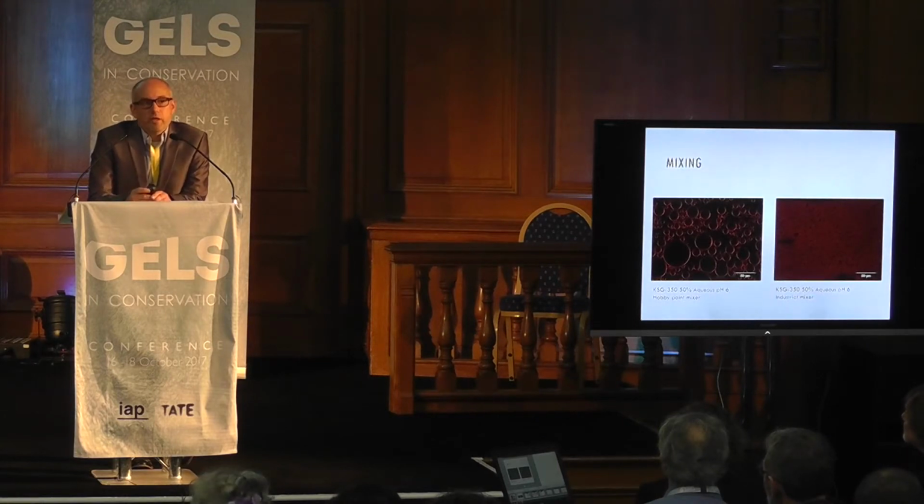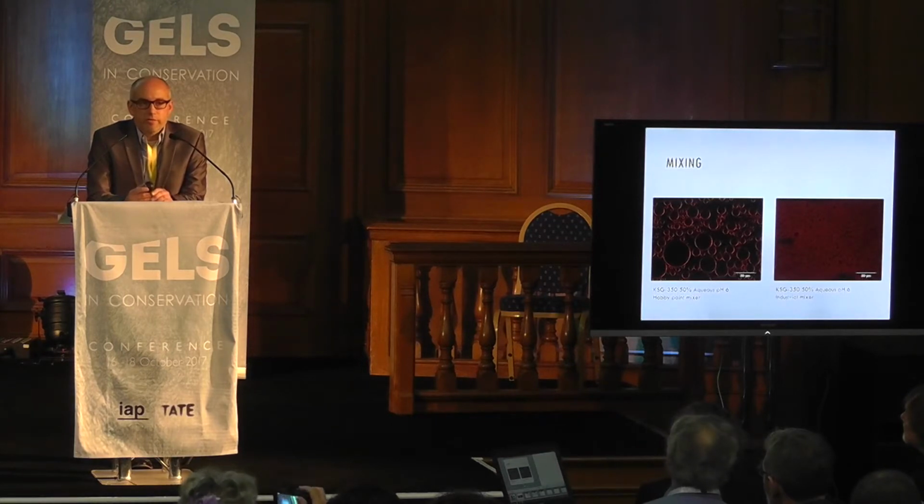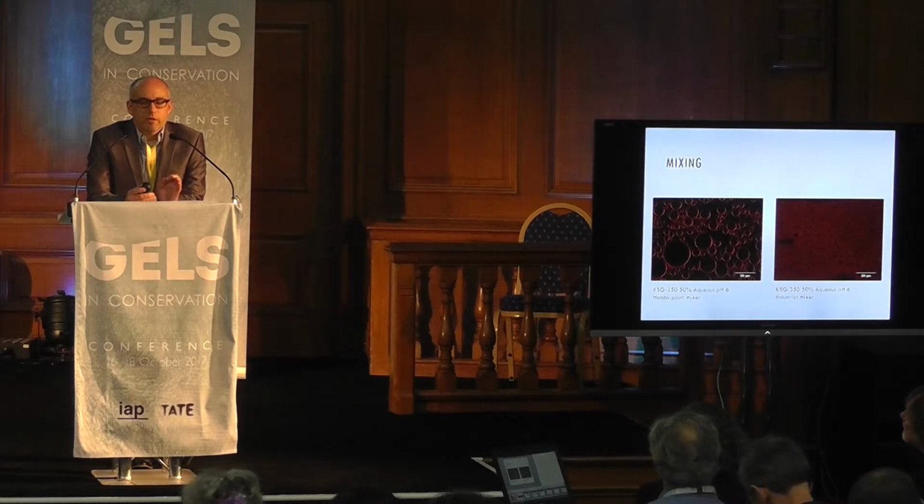One note on mixing. If you mix them by hand, shaking, sort of as Chris does, you're going to wind up with a situation that you can see on the left. You're going to wind up with an emulsion. It's going to look nice and creamy, but your particles are going to surround much larger aqueous phases. What Richard and I tend to do is use mechanical mixing, paint shakers, more energy going into the mixing process to disperse that aqueous phase through a larger percentage of that silicone solvent.